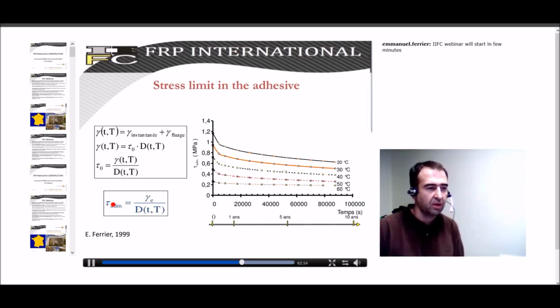This was the idea to fix an allowable shear strength, to get this kind of figure here, depending on time, level of strain, and temperature. You will have the limit in stress you should have, not in your FRP, but in the adhesive, to avoid getting the nonlinear behavior, to keep your adhesive in an elastic stage. If we observe this value, for example, at 20 Celsius degrees, our conclusion was that we should limit the serviceability stress in the adhesive at 0.7 megapascal, so that we avoid any debonding over a long time period. But if we speak about higher temperature, you can observe that the limits should be much lower.